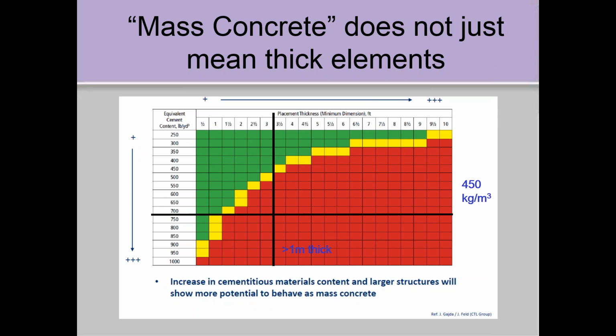So you could only be half a meter and still be on the edge of this if you have high cement contents. And of course, the green is good. Yellow is risky, but not as risky as red. But I think it helps put things in perspective because of the high cement contents and higher strengths that we're placing. Mass concrete isn't just big things anymore. And so thermal cracks are showing up in areas where we wouldn't have expected them 30 years ago.